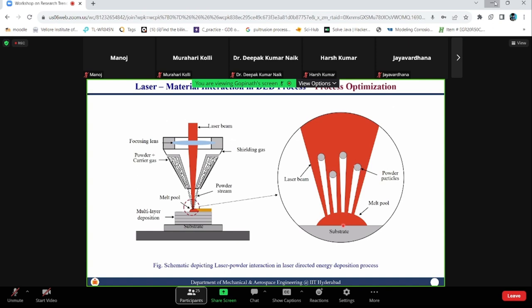Now, here what we are trying to do is look at this temperature. Again, this is an open loop system. It's not a closed loop. We are manually doing it. Here you see, every time the temperature of this molten pool is dropping down to the minimum detectable temperature, so you need not do anything. Just relax and watch the process. But after a few layers, like the 11th to 20th, you can see the heat accumulation has started happening. Now you have to react and do something.